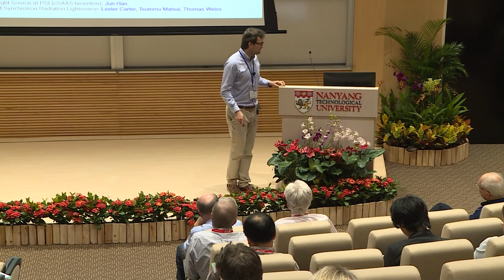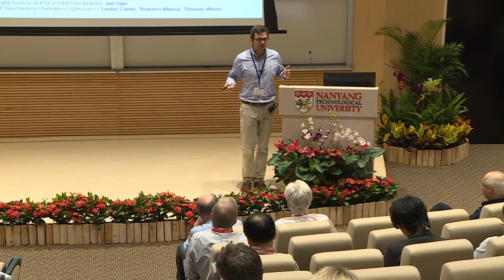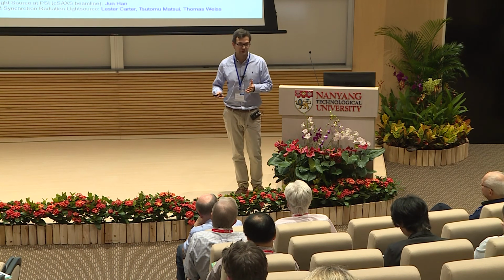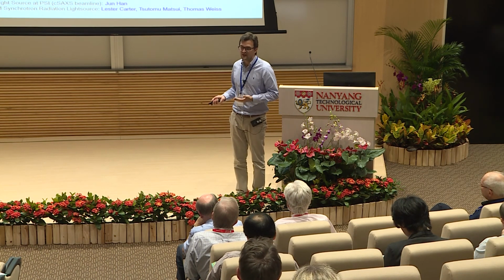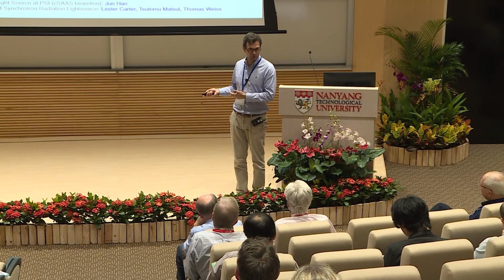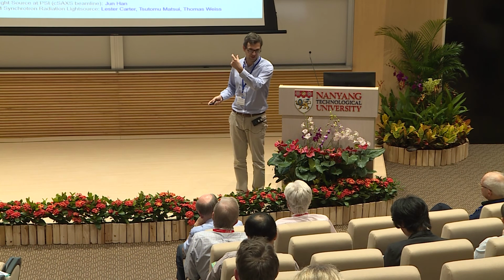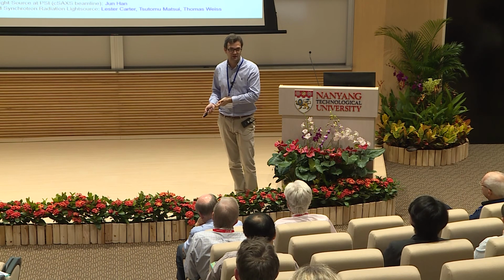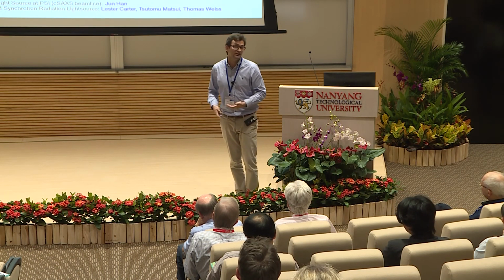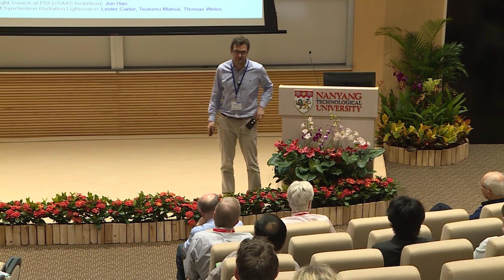The other one, yes. When we use PEG, the transfection efficiency goes down because we are reducing the interactions of our particles with the endosomes for them to be released. So that's the other part. PEG by itself seems to improve the circulation time a lot, maybe a couple of days, but it reduces transfection efficiency. So the next step is to functionalize the distal ends of PEG with better moieties for targeting, or then use something else. I mean, here we wanted to use PEG also as a model to make the point.